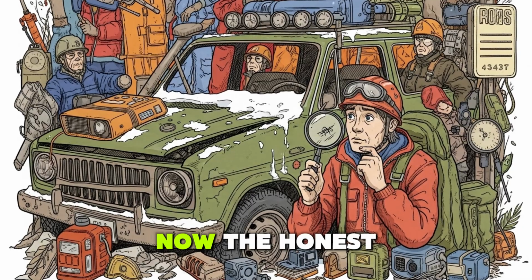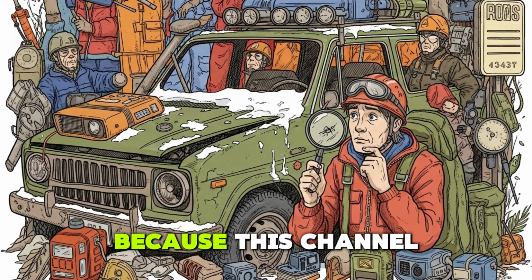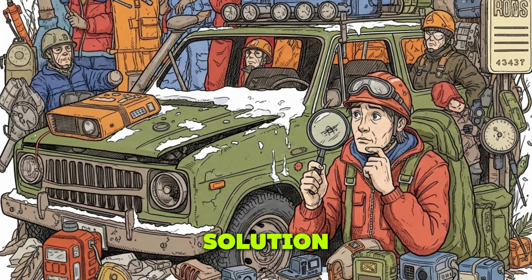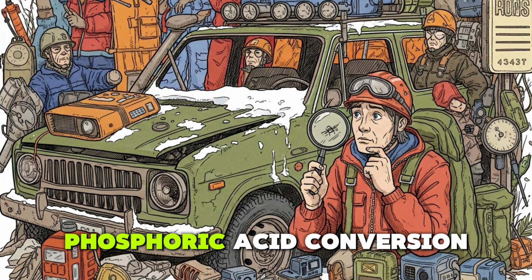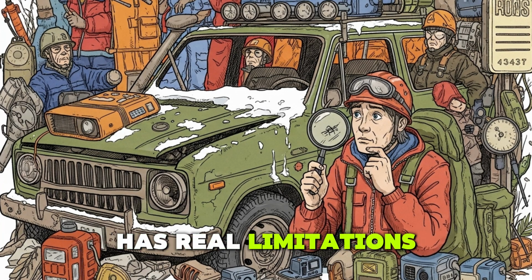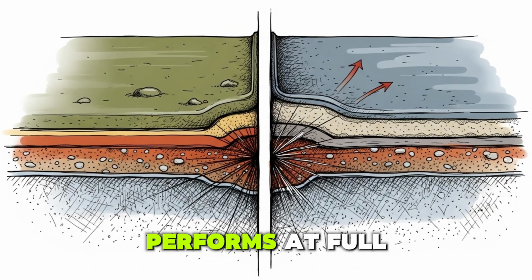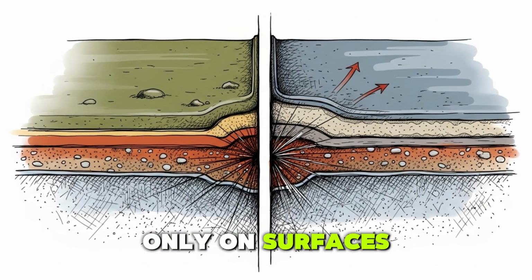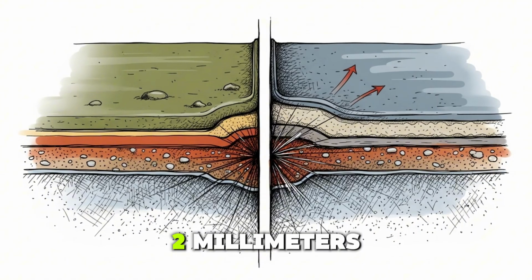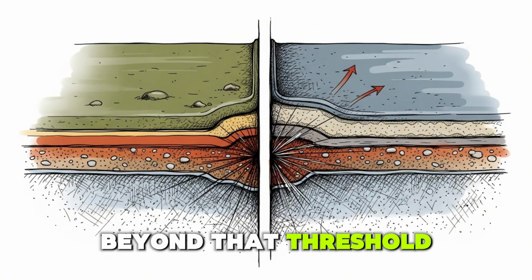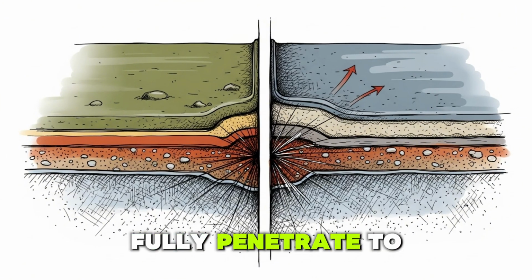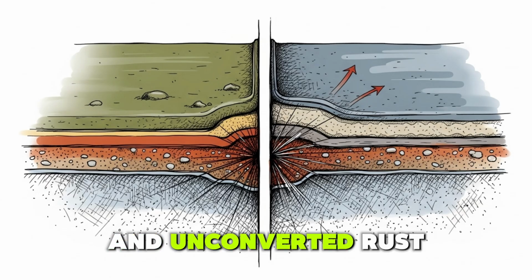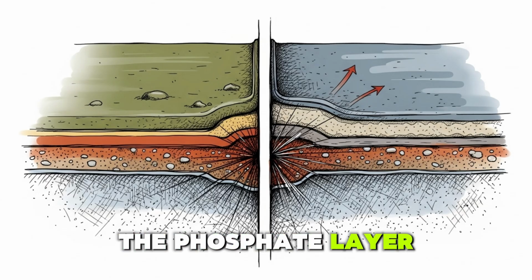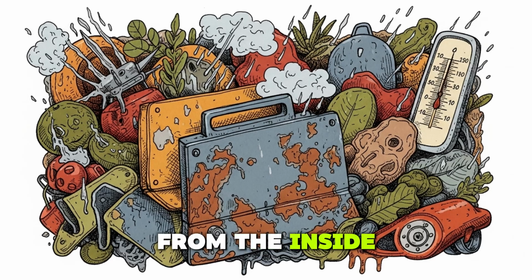Now, the honest part, because this channel does not sell you a perfect solution and walk away. Phosphoric acid conversion has real limitations that matter in the field. It performs at full effectiveness only on surfaces where the rust layer is no deeper than approximately 2 mm. Beyond that threshold, the acid cannot fully penetrate to the base metal, and unconverted rust remains trapped beneath the phosphate layer, continuing to expand from the inside.